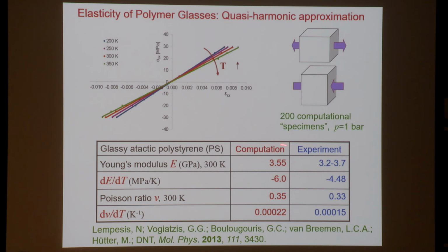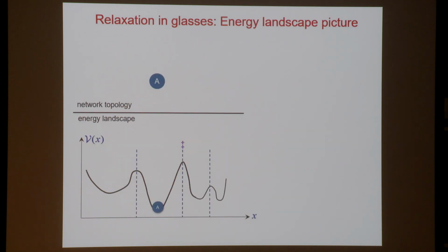So here we see the Young's modulus and its temperature dependence as predicted by deforming 200 such computational specimens confined in the minima. And also from the lateral contraction or expansion of the specimen, we can calculate the Poisson ratio and its temperature dependence. And overall, we can see that these are not bad when compared to experiment. Now, can we deal with this process of relaxation of the system slowly changing its properties as time goes by, because glasses are not in thermodynamic equilibrium?